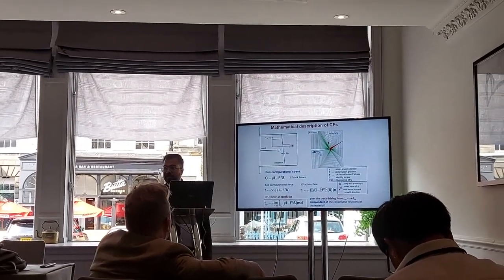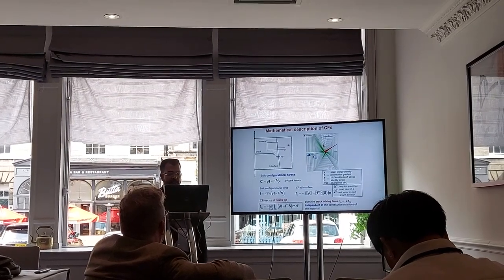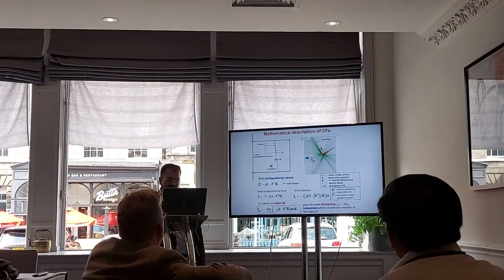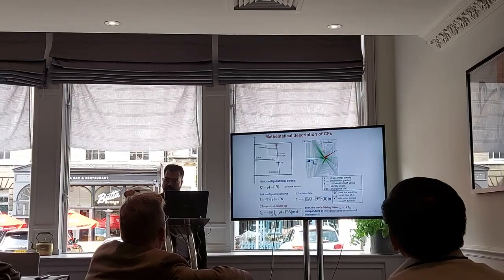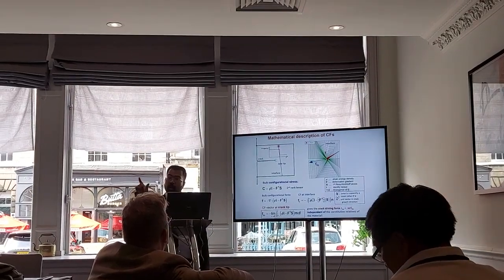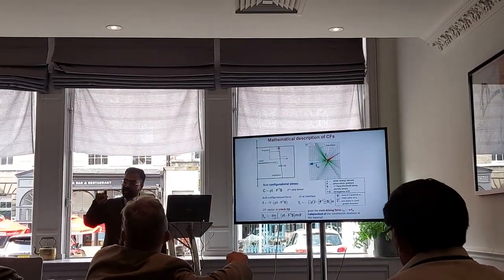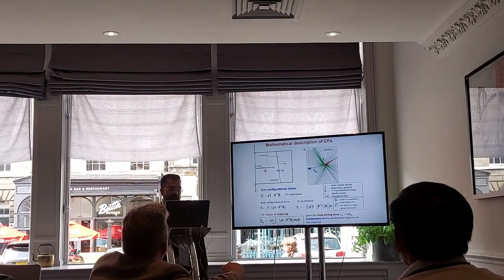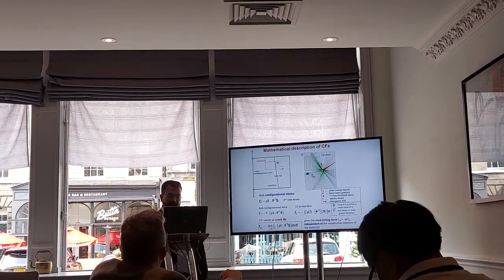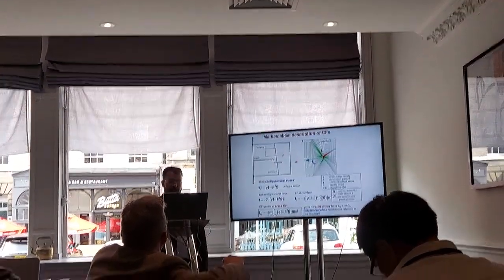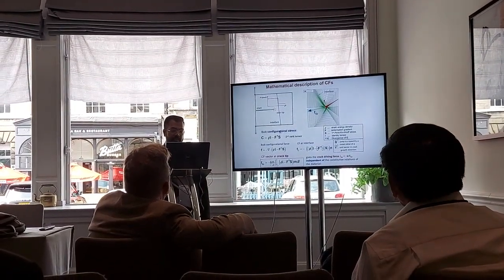If you have a change in material property, whatever energy you are supplying in terms of J far, which is the boundary dotted line in the green, is not equal to the energy which is available at the tip in the contour. If you calculate the J integral here and the J integral there, that will not be the same. So how do we calculate it? We calculate it using configurational forces.